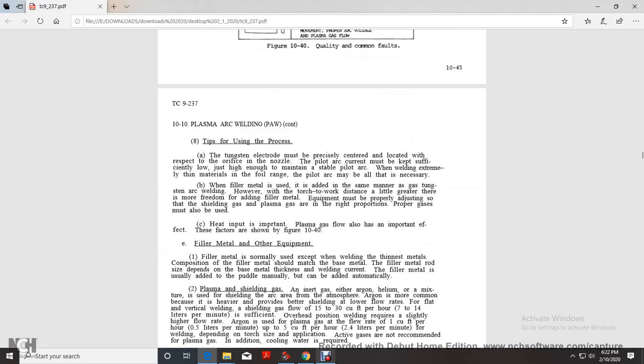Tips for using this process: the tungsten electrode must be precisely centered with the orifice of the nozzle to keep the pilot arc. The current must be kept sufficiently low, just high enough to maintain a stable pilot arc. When welding extremely thin metal, the pilot arc may be necessary. When filler metal is used, it is added in the same manner as with gas tungsten arc welding, however, with a lower torch-to-work distance.